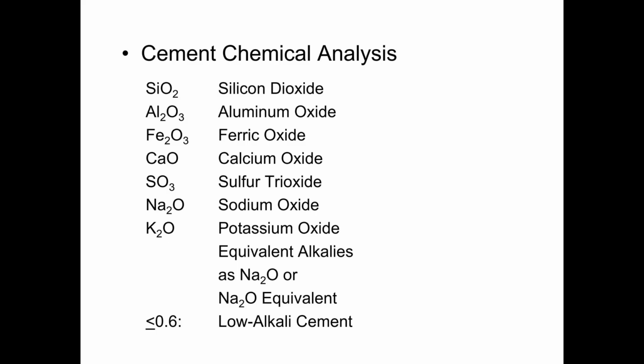The sodium and potassium oxides are not necessarily required to be indicated on the mill test report, but the testing is done by the cement supplier. So usually if I'm reviewing a mill test report and it doesn't give an indication of the sodium and potassium oxides or the equivalent oxides, that's a pretty good indication to me that it's probably pretty high content.